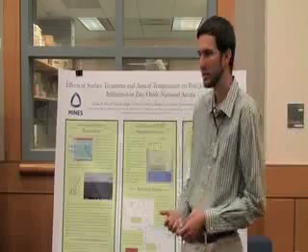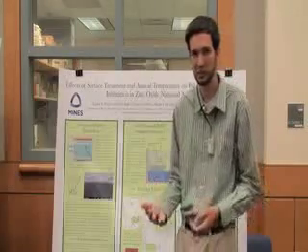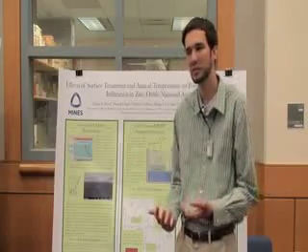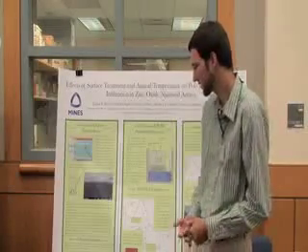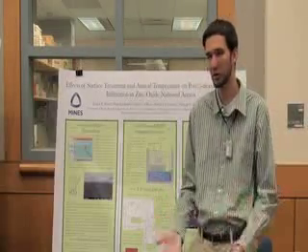The problem that we have with these is that the dissociation length of the exciton is about 10 nanometers, which is the reason why we have chosen zinc oxide to work with, because these zinc oxide nanorod arrays have a morphology of about 10 nanometers. And if we can intercalate the P3HT polymer into the zinc oxide nanorod array with 100% efficiency, then we can incredibly increase the charge carrier mobility and the photoelectric current of the solar cell device.